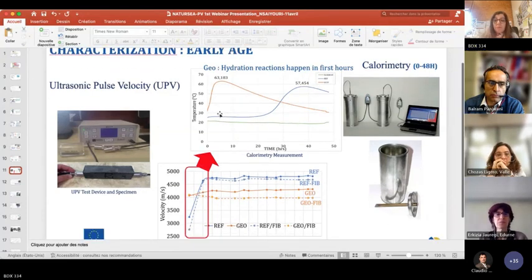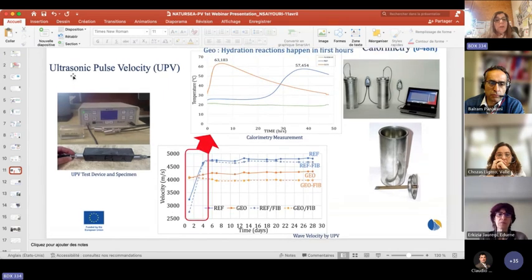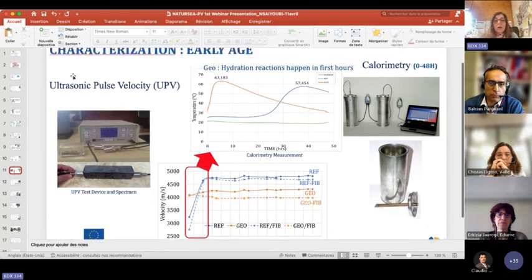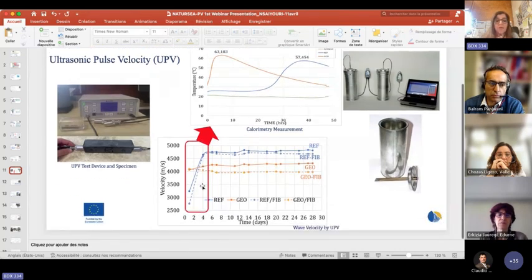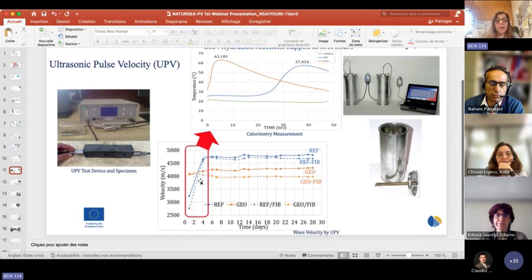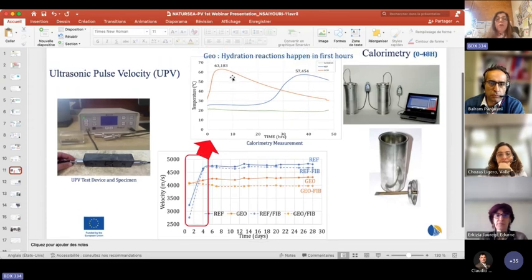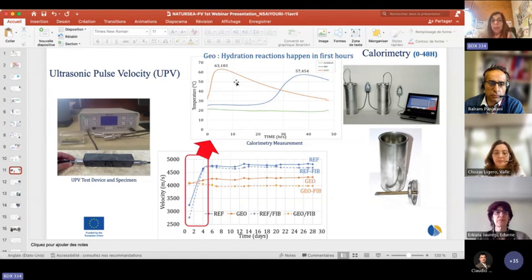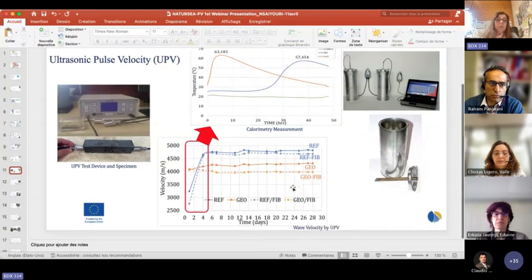We also have measurement with the ultrasonic pulse velocity in the first days, and we can see that in the first part from 0 to 2 or 3 days, we have what we can find here with that high temperature. Geopolymer hydration reactions are rapid, happening at the beginning of the process. We also have a high velocity observed here, and after we have the plateau for reference, and geo with and without fibers for this example.